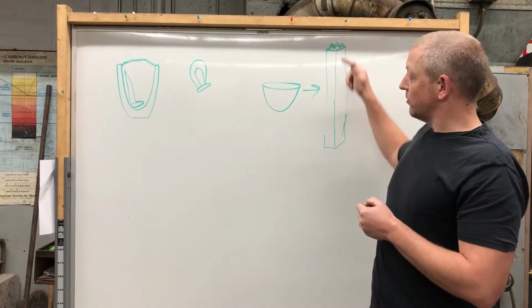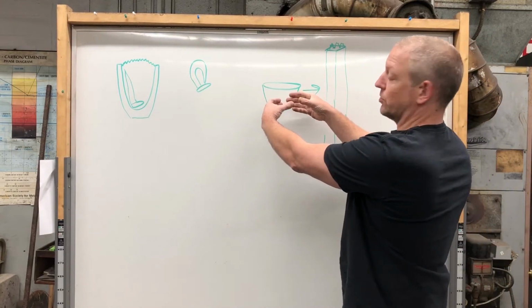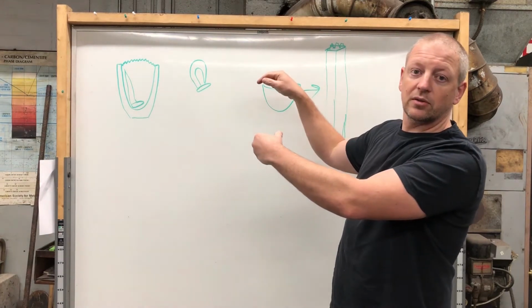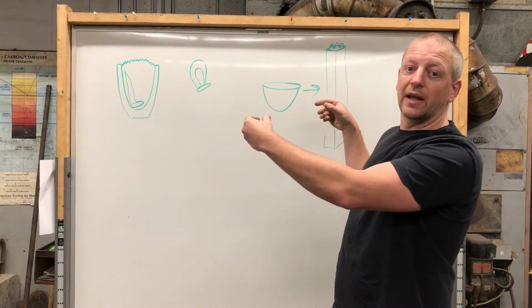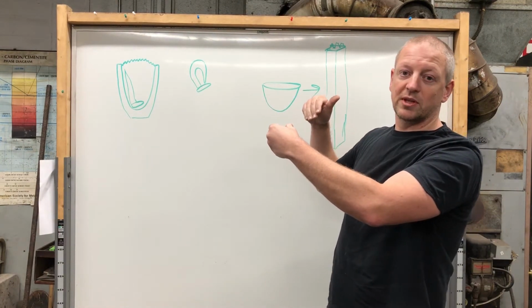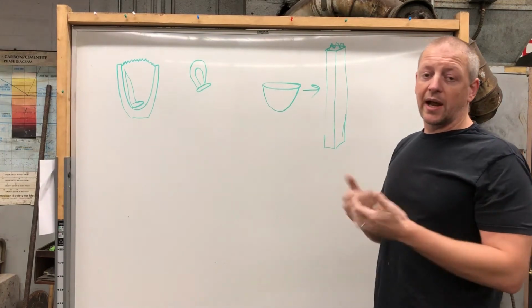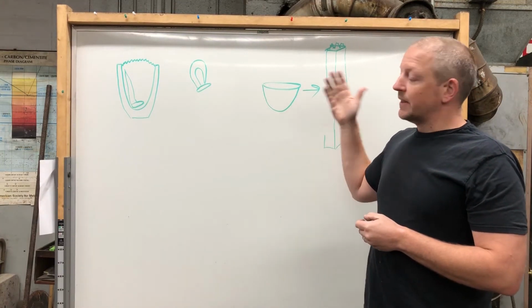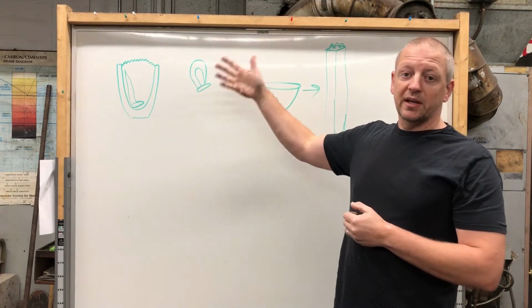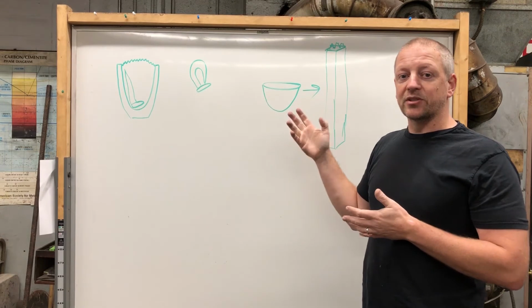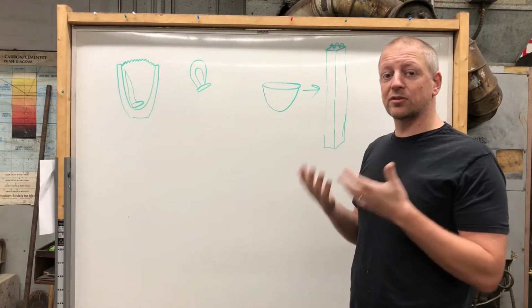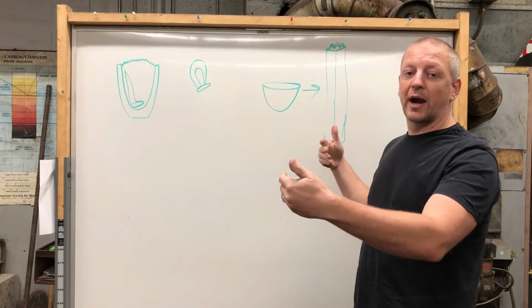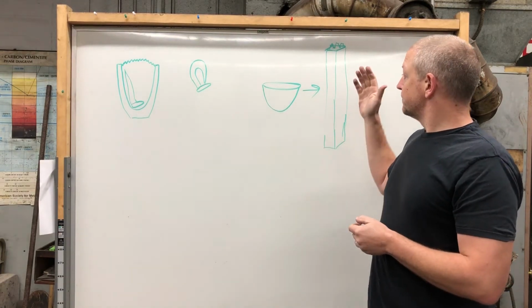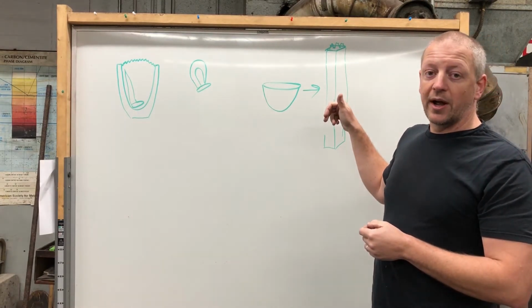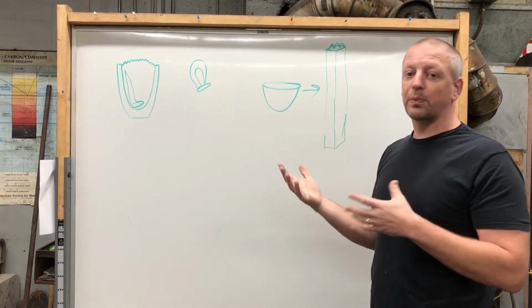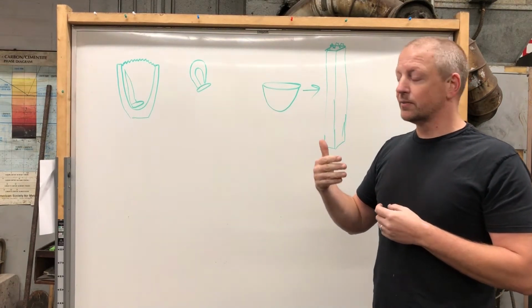It's a real advantage of forging out this direction. When you forge out the traditional way, if you've got cracking material, you've stretched it over the full length of your bar. Now you've got to grind down substantially if you want to get rid of that. Traditionally, they kind of just left it for the most part. As long as that was along the spine of a single-edged blade, it didn't have that much of a detrimental effect. Modern standards don't really allow for leaving giant cracking seams in your blade. So that's why I started forging out this other direction. I feel it yields a superior product, especially by modern standards.